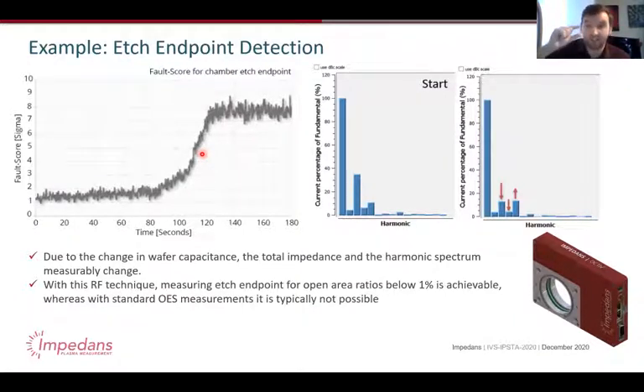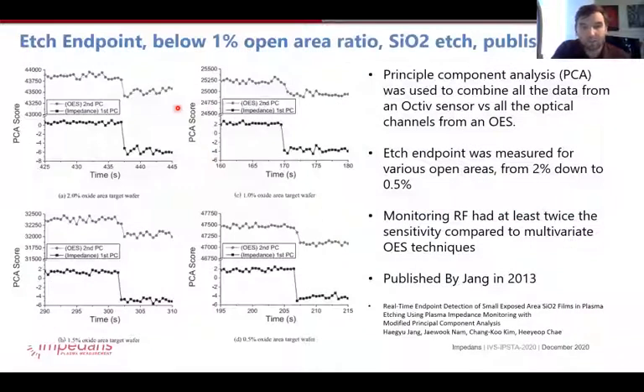So the change in the thickness of the wafer, the change in the capacitance, is quite easy to measure with these high frequencies, with the radio frequency you're powering. There have been a lot of publications on this over the years, because companies like Samsung and SK Hynix are at the stage where they're making features so small that they need new detection methods. They're showing that monitoring the impedance and harmonics gives you at least twice the sensitivity of optical sensors as you go to these small open area ratios. And the same technology can be used to monitor deposition. It's the same in reverse.